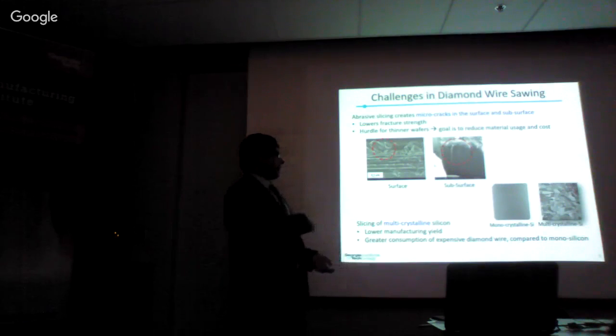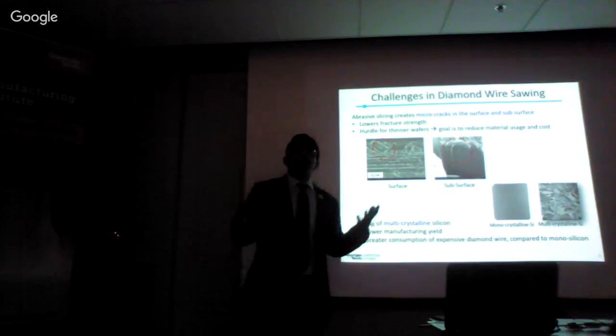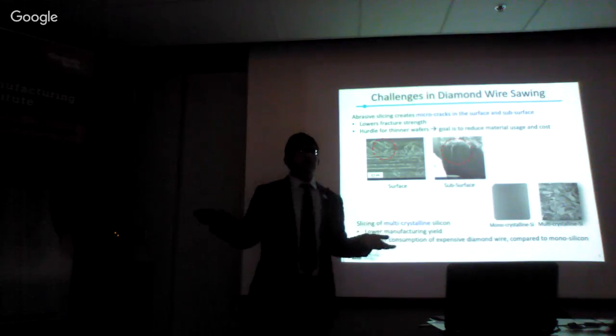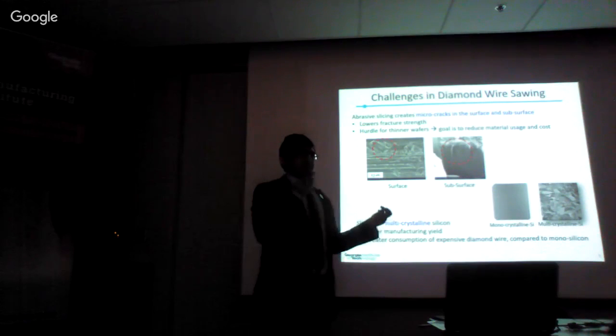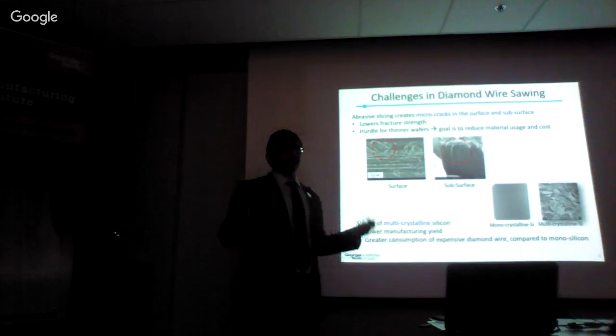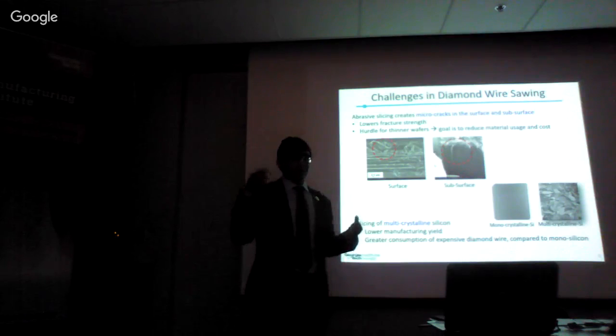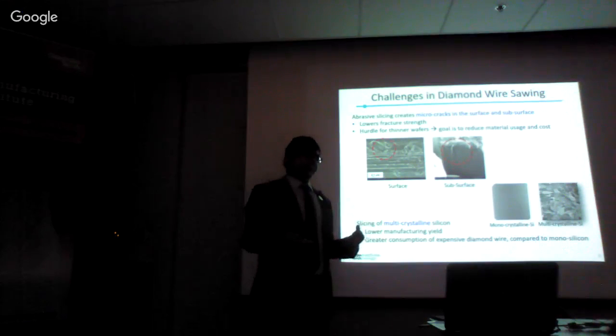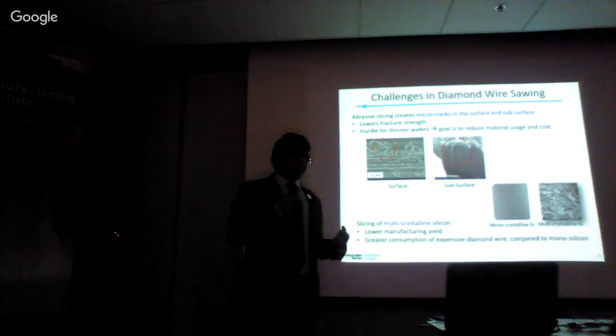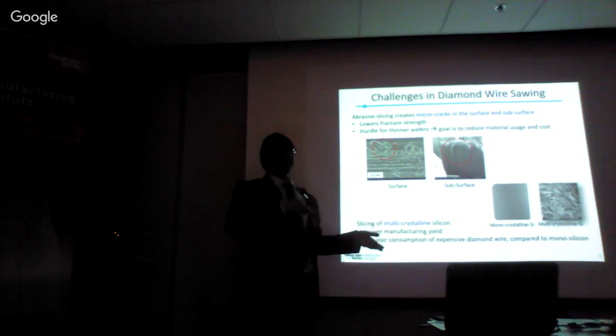One of the prime challenges in cutting multi-crystalline silicon is lower manufacturing yield, which means if you cut 100 wafers of multi-crystalline silicon, maybe 20 or 30 will go to waste because they break while cutting. Whereas for monocrystalline silicon, the manufacturing yield is much more. Maybe 5 or 10 wafers would go to waste. And secondly, more critically, for manufacturers who are cutting the silicon wafers, there is greater consumption of the expensive diamond wire when cutting multi-crystalline silicon compared to cutting monocrystalline silicon.